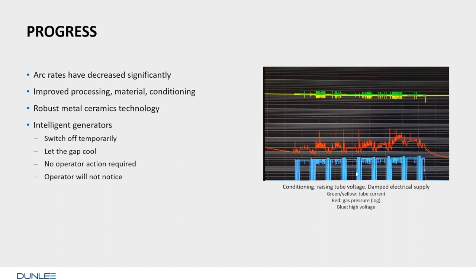We process the tube. The tube learns to live with a high voltage because once you have conditioned it and reduced the voltage again, the arc activity decreases. So the progress over time, arc rates have significantly decreased in the past. Processing is better, material and conditioning is better. Robust metal ceramics technology has been introduced. And last but not least, we offer intelligent generators. That's why a package of generator and tube is so important.